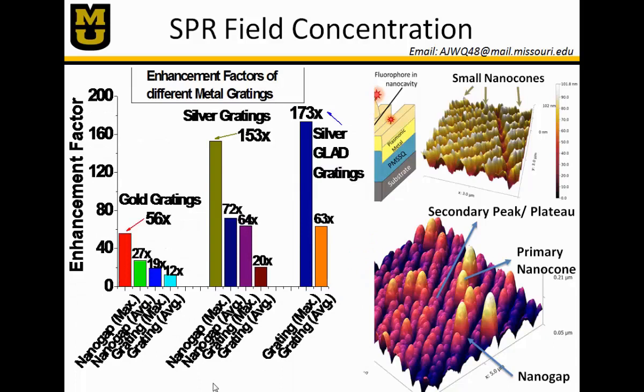And this can be seen in the enhancement factors of different material types or different metal types that are deposited on these gratings. Gold gratings have been shown to have an enhancement factor up to 56 times, while silver gratings can have 153 times enhancement for fluorescence, and that's due to the lower plasmonic losses of silver films. And then by incorporating these other nanostructures, you can get enhancement factors up to 173 times that of fluorophores that could be found on flat glass substrates.